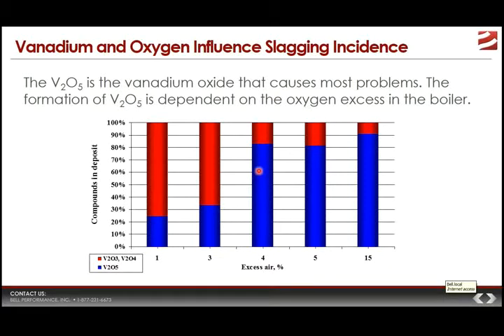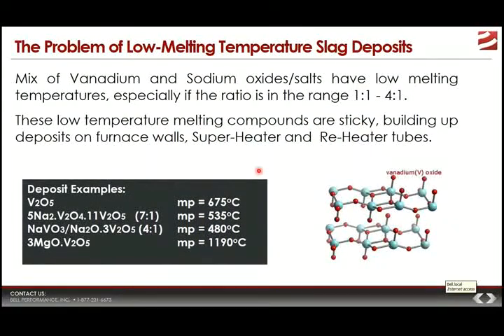And of course, if they're trying to keep the V2O5 formation low, they can't just decrease the amount of oxygen indefinitely, because lowering the oxygen content can lead to other problems in itself. Namely, it will directly impact the completeness of combustion of the fuel. So the operator here is already having to strike a balance between providing enough oxygen for combustion, and on the other hand, minimizing the formation of problematic deposits that have low melting points. And low melting point deposits are a key contributor to many of the problems that fuel oil users are trying to face. So let's look at them.